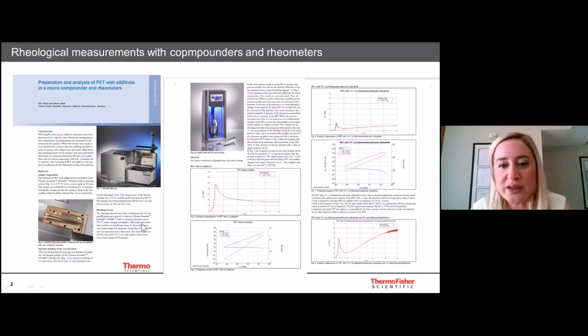So here you see PET with no additives. This first part is related to the feeding, and then you see that the pressure drops and viscosity drops, and it ends at around 18 bars. So we also see the oscillation data with the loss, G prime and G double prime.